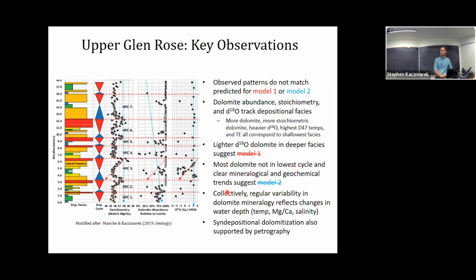And here's what we see. Instead of these top-down patterns, what we see in fact is dolomite abundance and dolomite stoichiometry that are very cyclical, such that the observed patterns don't really match those predicted for either model 1 or model 2.